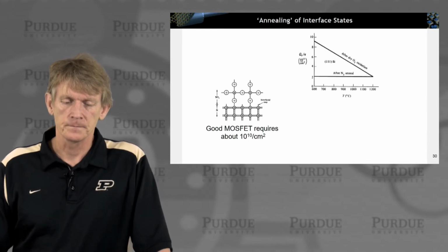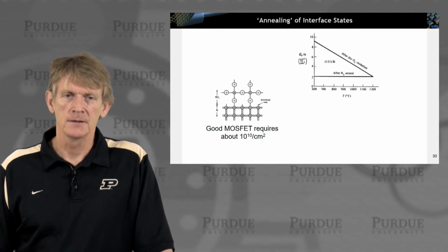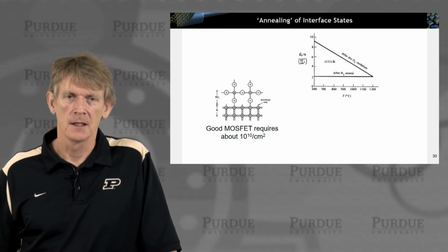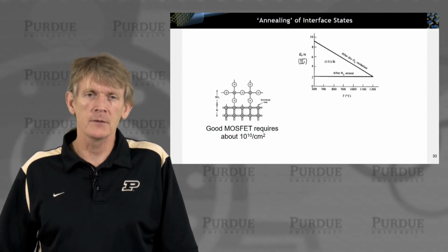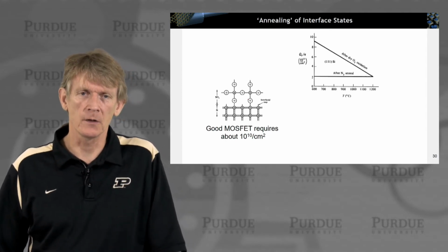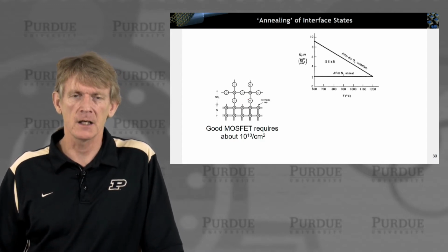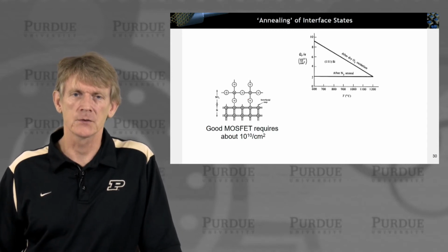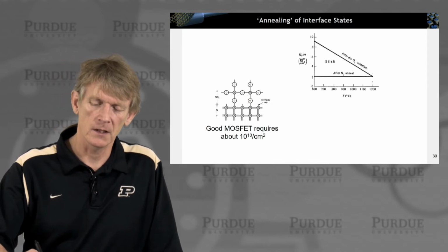So if you oxidize at higher temperatures, you have more atom motions, so to speak, and then the oxygens will have more time to explore, in thermal vibration, a phase space that is larger, and they can eventually find the optimal connectivity to the underlying silicon. So you will passivate more bonds if you oxidize in dry conditions at a higher temperature.